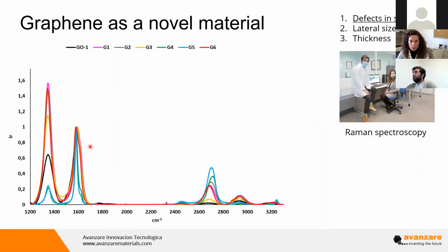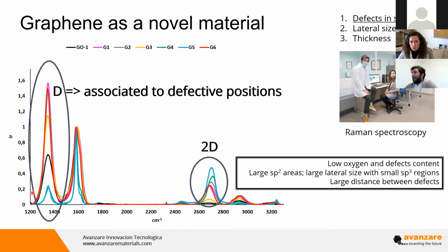What we do to analyze the quantity of defects of a material is acquire Raman spectra. Here is myself together with my colleague Boyan, working on the characterization of some graphene. For example, you can see here in the spectra two typical bands. One is associated with defects, called the D band, and the higher its intensity, the greater the quantity of defects. I need to say that there is a lot of theory about this technique, but as a first approach, the more intense this band, the more defects. Also, the other band is important to analyze the quantity and the quality of the graphene.